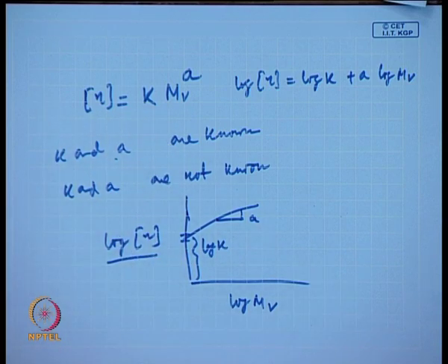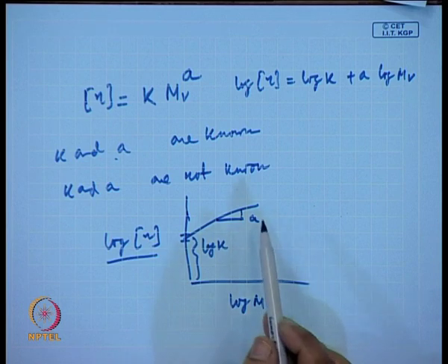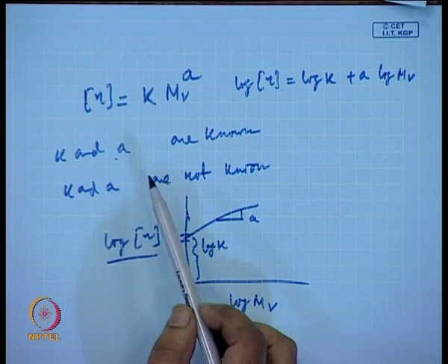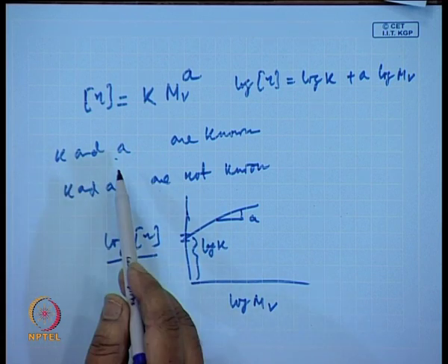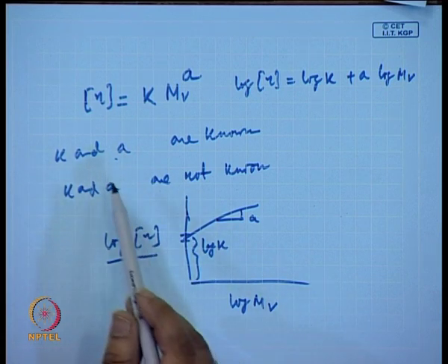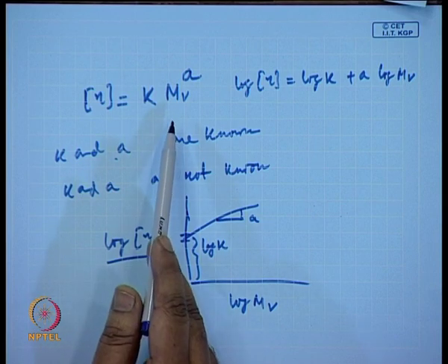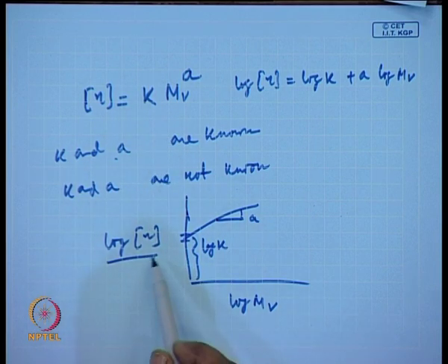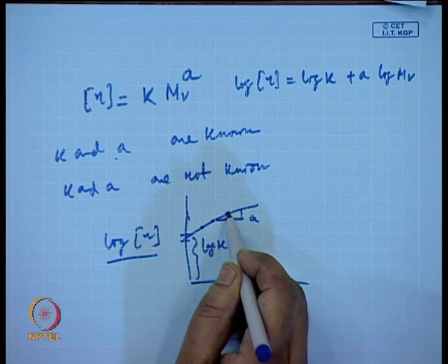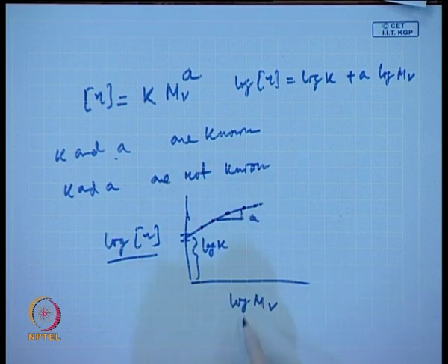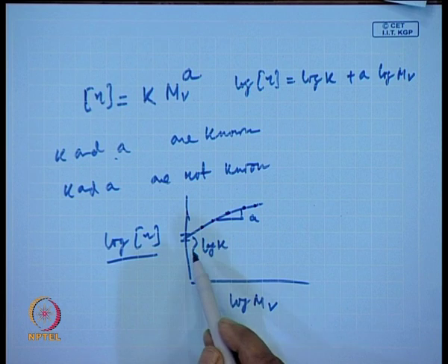You can determine experimentally the value for intrinsic viscosity, and you can utilize this expression to get the viscosity average molecular weight. But if somebody has not done it before, for an unknown sample where K and a are not listed, how do you determine the viscosity average molecular weight? Then you need to plot the log of intrinsic viscosity against many known molecular weights.